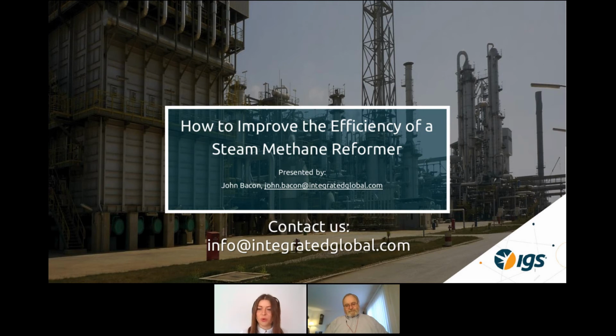Question from Abid. What would be the effect of applying the ceramic coating on stack temperature? If you use the ceramic coating to reduce fuel consumption, it will reduce stack temperature in the same way that it reduces the convection section temperature, because you're absorbing more duty in the radiant section. The flue gas temperatures will be lower. I think in one of the case studies, you might have seen that the stack temperature came down by 8 degrees centigrade. So not a whole lot of reduction, but a significant reduction for a stack temperature.